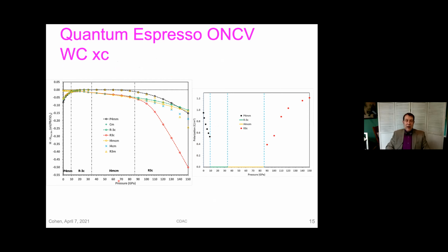So we've spent quite a bit of time trying to understand this, and these are our latest results. Finally, Yangzhen Lin has been working with me on this to try to wrap all of this up. And what we did was be very careful with our pseudopotential generation. And these are pseudopotential results shown here. But the other thing that we did that I'll be showing you is that we compared with all electron full potential LAPW in order to really make sure that there was no issue with pseudopotentials. It turns out that the pseudopotentials are really key to getting very accurate results here.